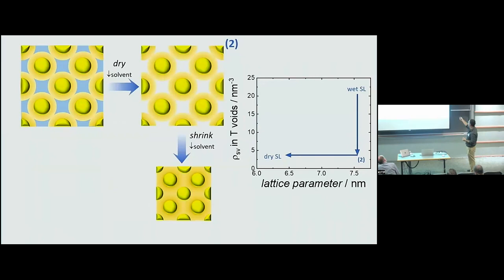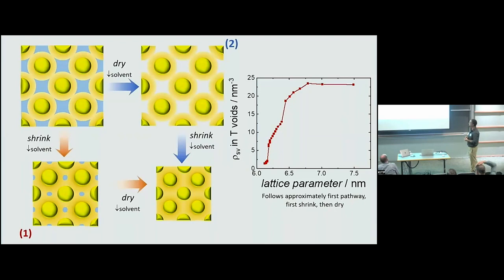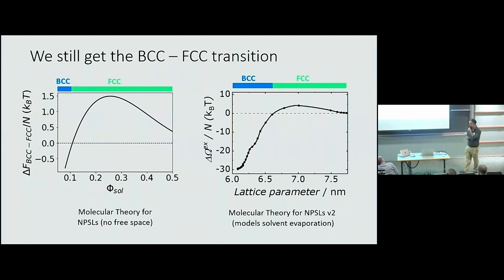And these are the predictions of the theory. Basically, it's, I would say, closer to the first one. So first you shrink the superlattice. Of course, again, each of these points corresponds to a different value of the chemical potential. You are losing solvent all the way. And then, as I said before, you first collapse, and then you dry. So this was good for us because it means that the first approximation that we used wasn't that bad. And also, we, of course, look at the BCC-FCC transition.